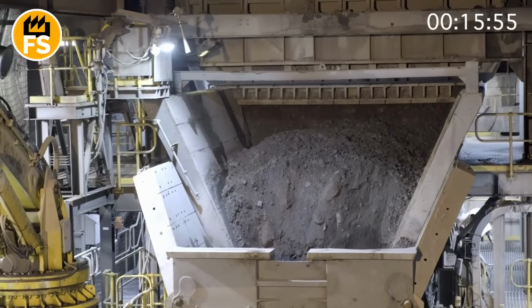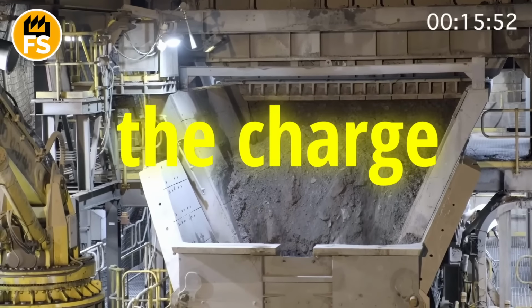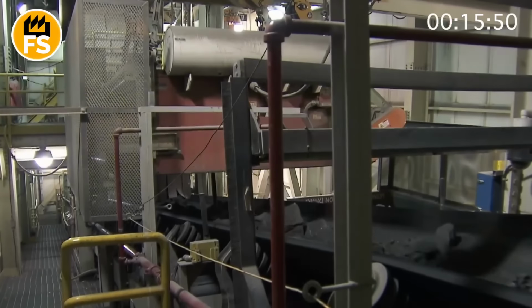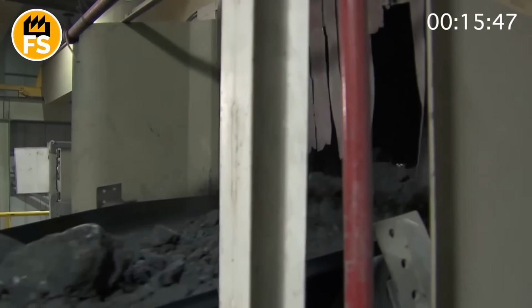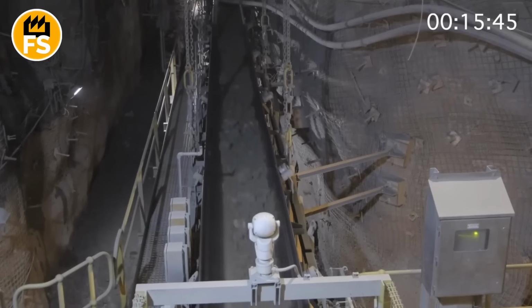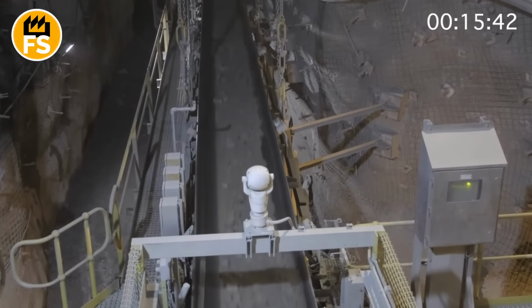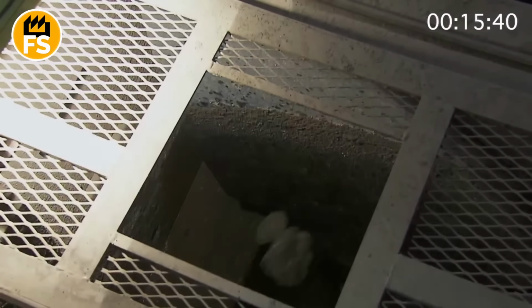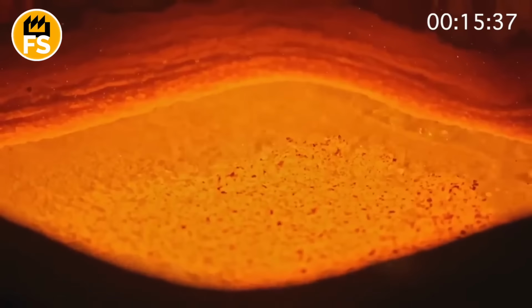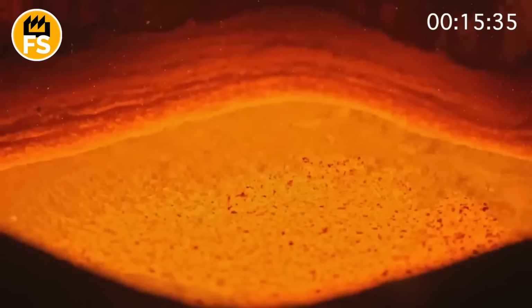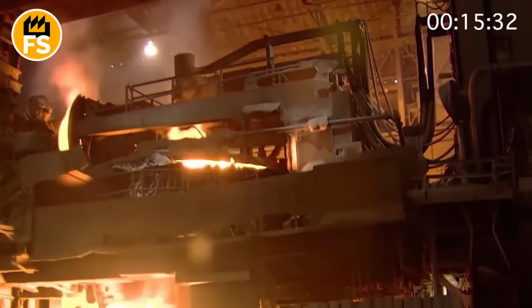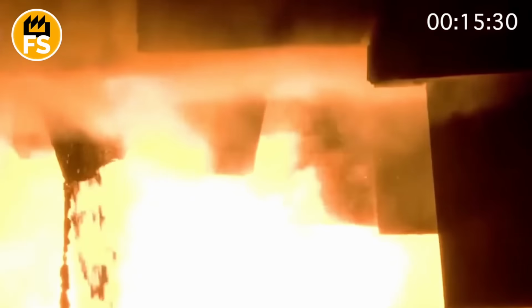The prepared mixture of ore, coke, and flux, called the charge, is continuously fed into the furnace, completely submerging the ends of these electrodes. Hence the name submerged arc furnace. A colossal electric voltage is applied to the electrodes. But unlike a steel-making furnace, here the arc does not burn openly. The electric current passes through the charge itself, which resists it, and from this heats up to incredible temperatures, over 3,600 degrees Fahrenheit. Inside this white-hot cauldron, a real chemical battle begins.